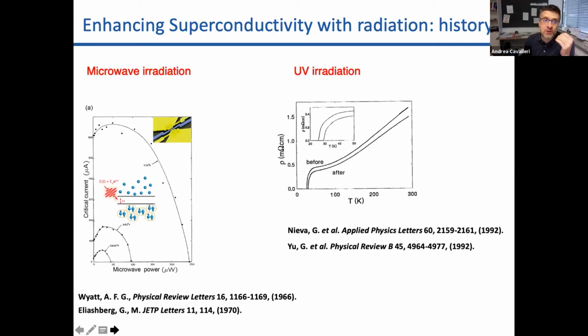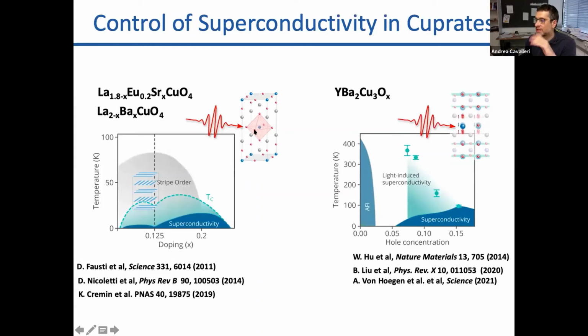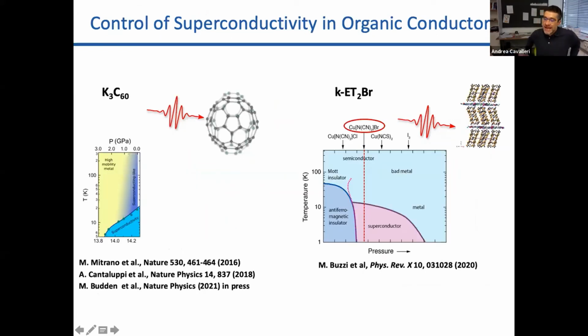What we have done in the last few years has been to apply phononics to try to do something similar in a more rationally designed way, to try to control the crystal structure. We've done work in cuprates, which I will not talk about, except to mention that when you excite YBCO with specific phonons, you can induce effects that look like transient superconductivity up to really very high temperatures. This is a completely different story that I will not be discussing. What I would like to get to instead are the experiments in which we've used resonant excitation of certain molecular vibrations, both in the doped fullerene superconductors and in certain kappa charge transfer salts, using light to drive vibrations to try to enhance superconducting features in these materials.